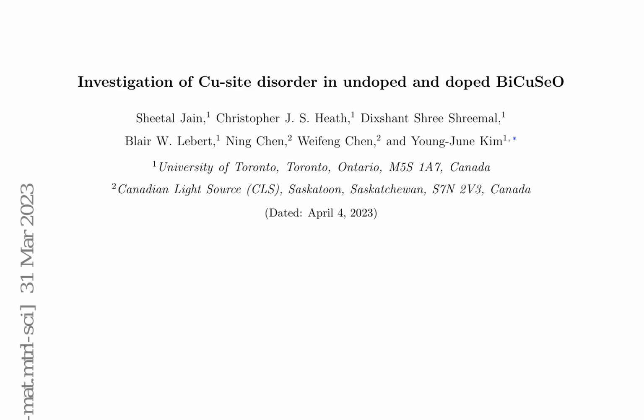Polycrystalline, powder, samples of undoped BiCuSeO, Ag-doped BiCu1-xAgxSeO, and Pb, Ag dual-doped BiCuSeO, Bi1-xPbxCu1-xAgxSeO, were synthesized via a solid-state reaction process. Raw materials, including bismuth 3 oxide, Cu, lead 2 oxide, Ag, and Se powders, were mixed and ground in an agate mortar and pestle. The mixtures were then pressed into cylindrical pellets under 50 megapascals, sealed in quartz tubes under